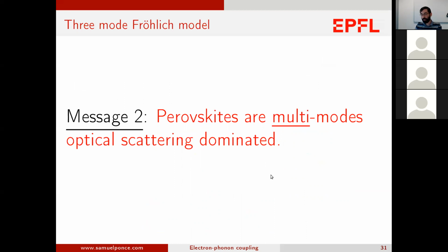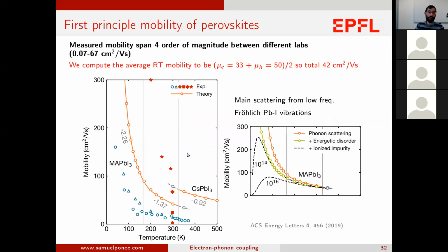We've also shown that if you use a Fröhlich model with only one effective phonon mode, you will not be able to accurately reproduce the ab-initio result. The minimum number of modes you need is 3, in the case of MAPI and also in the case of cesium lead iodide. May I interrupt you, Samuel?